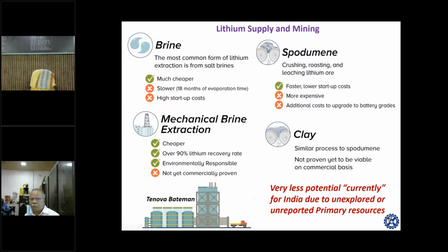Followed by mechanical brine extraction. Tenova and Bateman collaborated together to set up a plant where they achieved a nearly 90% lithium recovery rate. The plants which are running in Bolivia and Chile have got nearly 68% recovery rate, but this is a very recent development, 2020, where they have got a 90% recovery rate. But it is not yet commercially established.